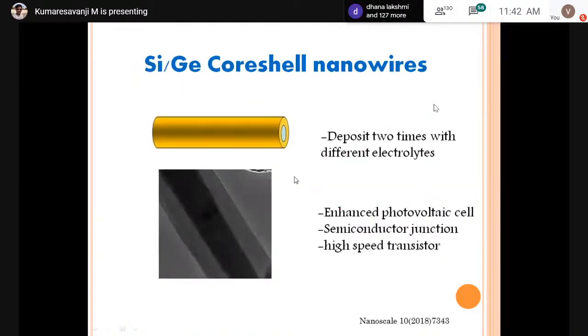Another important thing is core-shell nanowires. Here I show the deposition of core-shell nanowires. First, you prepare the nanotubes with one electrolyte, then clean it. Then you put in another electrolyte that you want to deposit inside the nanotubes. By electrodeposition, the other material will deposit inside the nanotube. This is called core-shell nanowires. So you have to do this with two different electrolytes, two times. This kind of core-shell nanostructure enhances the photovoltaic cell, also acts as a semiconductor junction, and is used as a high-speed transistor.